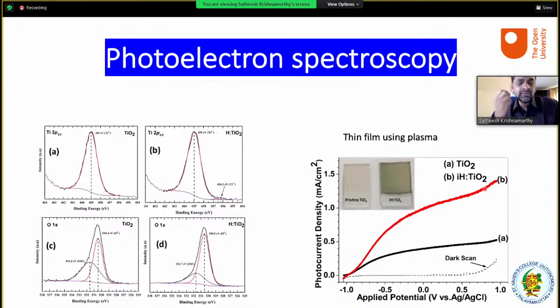And we do the fingerprint experiments, X-ray photoelectron spectroscopy. So we use X-rays, which act as photons, light, for spectroscopy. So we use light to understand the chemical bond. I told you earlier in my slides that the chemical bond plays a major role in understanding the properties of the system. So here on the left we have titanium 2p. Titanium 2p means 2p orbitals, and we probe the 2p 1/2 and 3/2 orbitals.